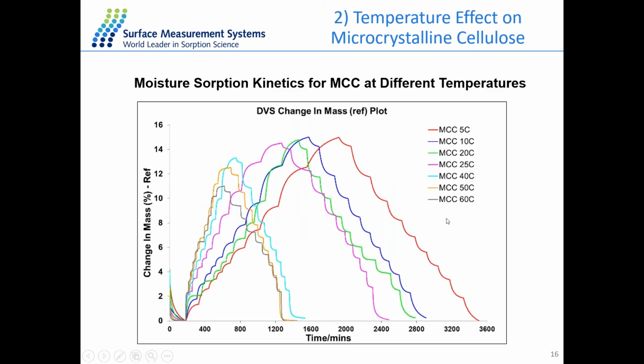And here are the results for all the temperatures. So different colors for different temperatures. Between 5 and 25 degrees, the moisture uptake at a particular relative humidity doesn't show a significant difference, but the time to reach the equilibrium is much longer. And then from 40 to 60 degrees, the result shows that with the increase in temperature, the moisture sorption capacity decreased a lot, which is probably due to a structural rearrangement.